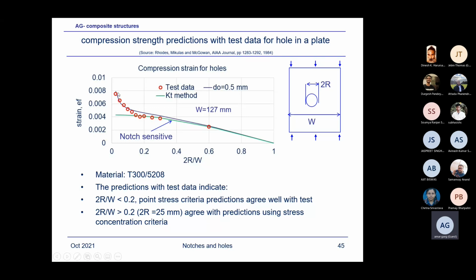As you can see, for a compression test panel they had done for certain layups, for T300-5208 material, I should have written the layup. I have not written it, but I can put that in my revised slides. So you can see here, this is test data, and this is a point stress equation, which I have shown you earlier, with proper finite width correction factor applied. This is W equal 127 millimeter panel and with holes of different sizes.